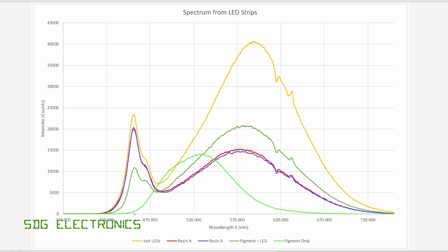So this light green peak over here is the spectrograph of just the glow-in-the-dark pigment glowing with no LEDs on. And what we can see is we've got quite a lot of light, quite a wide band, centered around 520 nanometers, which is why we get that nice green color. But it's not a pure green, it's spread out quite wide, which is why we get quite a lot of usable light from this glow-in-the-dark pigment. But basically when the LEDs are on, that pigment is stealing the light in the 450 nanometer region because it is excited by close to UV light.